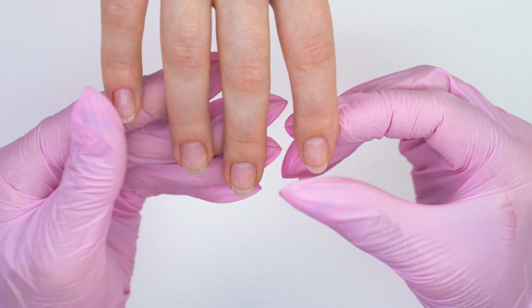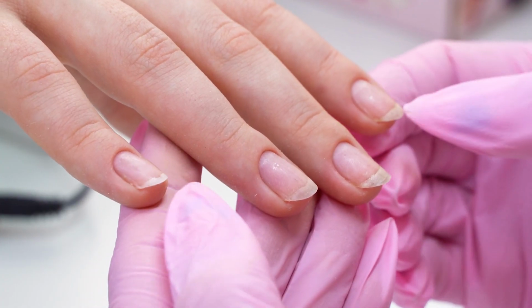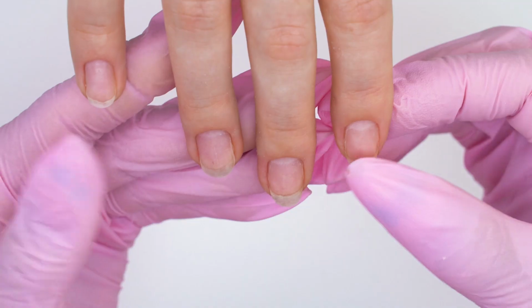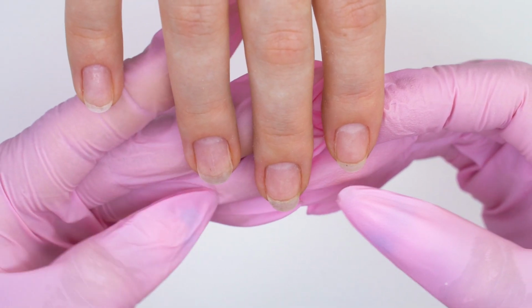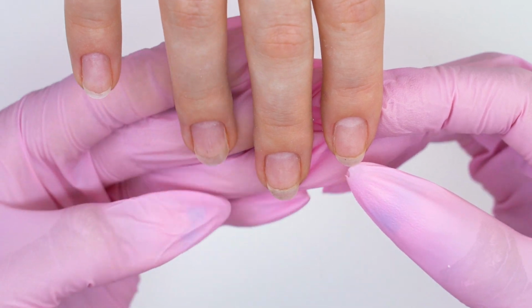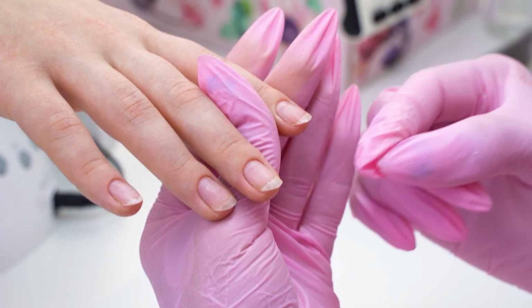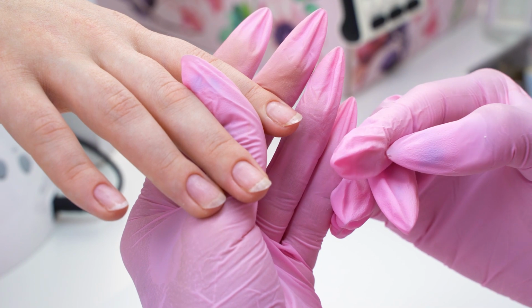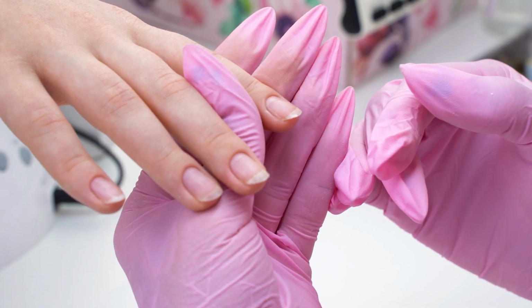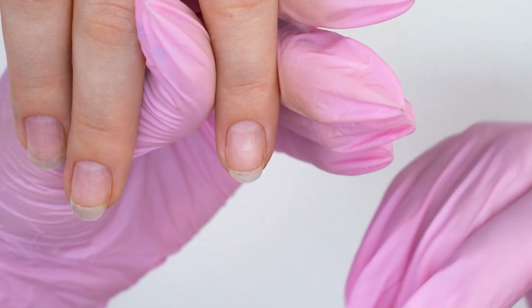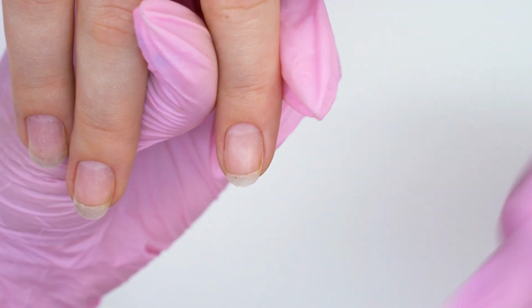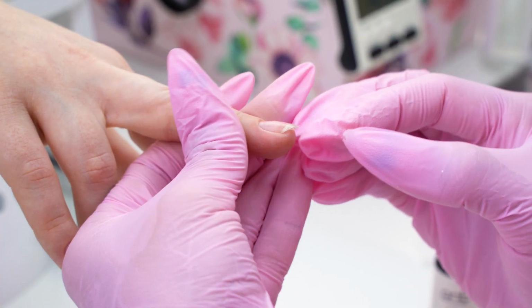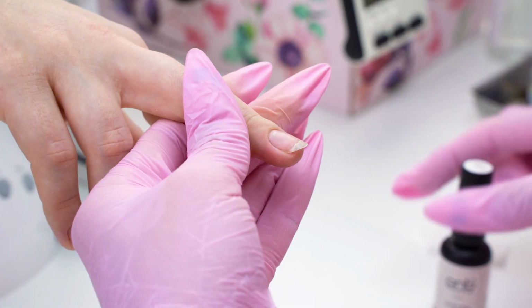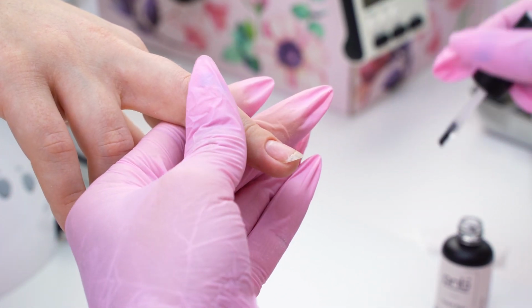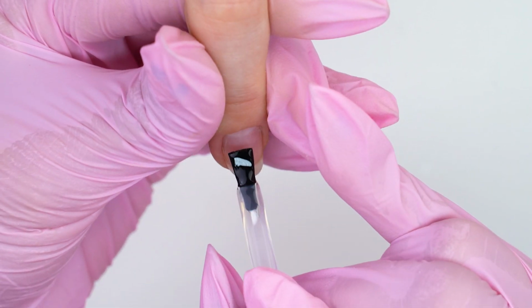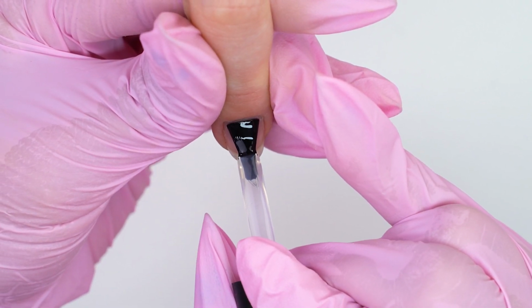Since my model's nails are very flexible, I need to use a rubber base coat for the underlay. The nails are not too long, so we can do a rubber coating here. If they were longer, I would use a rubber base coat for the underlay and a harder one for alignment. I could also use any sculpting gel or acrygel. For the nails not to bend, we need to build up the correct architecture. Right now, this nail is too flat, so I need to fix it and move the highest point closer to the cuticle.